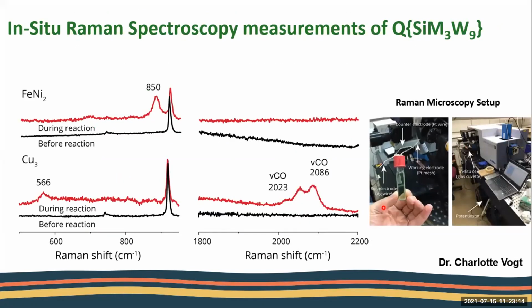When we try to measure in situ Raman during electrolysis, and this measuring was done in collaboration with Dr. Charlotte Vogt, we measured that by using a cuvette with 3 electrodes, as you can see here in the picture, and we saw that with the copper 3, we got species of CO that disappear in iron nickel 2. That means that we have this species here, and in the iron nickel 2, that is the reverse catalyst, as expected, we don't have it. Another peak that we got is this peak that does not appear in copper 3, and it may be related to CO2 minus species, but we are not sure about that.